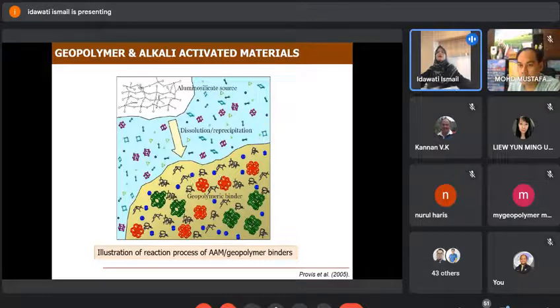who then look into details of how these materials, such as fly ash and others, especially with high alumina and silicate content, behave, how they react, and what the end product of the binding gel will be. So this is an illustration from Provis in 2005, who illustrated the reaction process of geopolymer binders. This is, I believe, high silicate and alumina content mixed with silicate or hydroxide, and all the species from the aluminosilicate sources will dissolve, and then they rearrange themselves with the sodium or silicate that's provided, and we'll have a kind of 3D network of geopolymeric binder. So silicate and aluminate rearrange themselves to become a hardened binder.